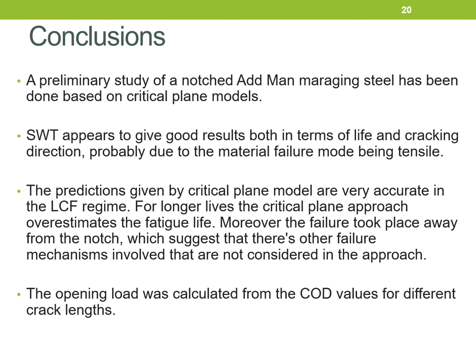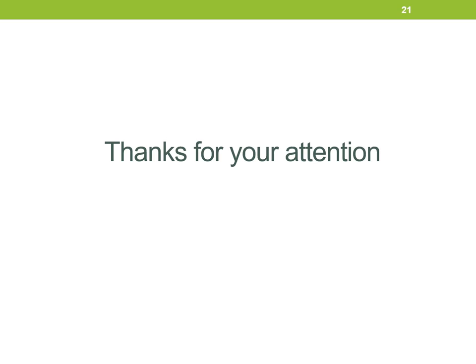The conclusions are: a preliminary study of notch fatigue in additively manufactured maraging steel has been conducted based on critical plane models. Smith-Watson-Topper appears to give good results both in terms of fatigue life and cracking direction, probably due to the tensile failure mode of the material. Critical plane model predictions are very accurate in the low cycle fatigue regime, but for longer lives the approach overestimates the fatigue life. Moreover, failure took place away from the notch, suggesting other failure mechanisms not considered in the approach. The opening load was calculated from COD values for different crack lengths. Thank you for your attention.